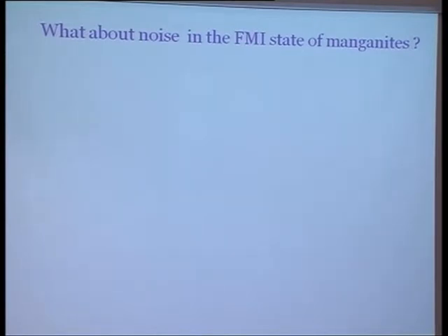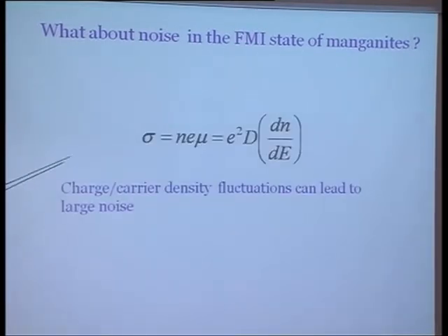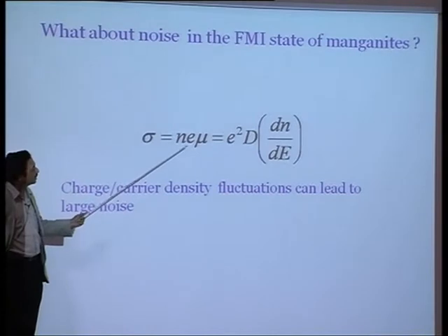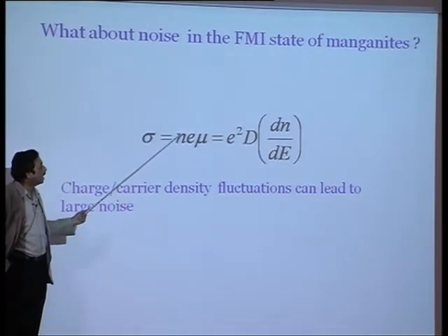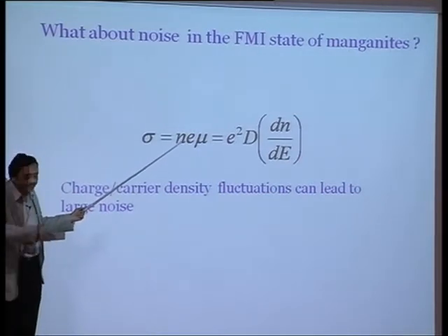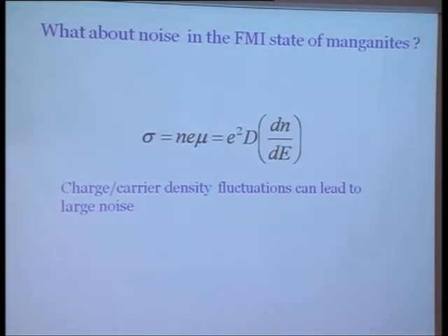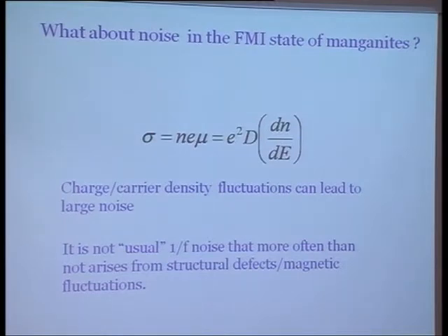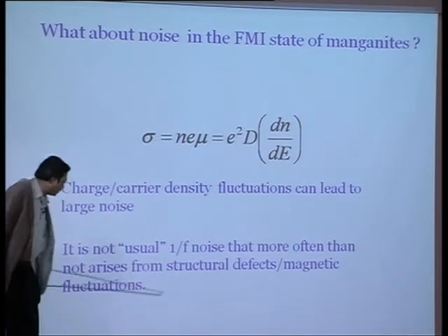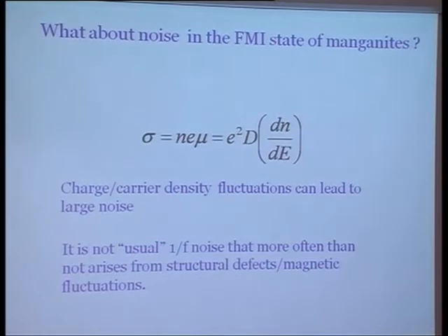So what about the noise in the ferromagnetic state of the manganite? Let me come back to this equation which Arindam has also shown, and which all of us born in the solid state physics community regard as our Bible. Here, just to tell you, you can get a conductance fluctuation either from this or from that. When you talk of universal conductance fluctuation, you are actually talking of fluctuation in the mobility, and the type of fluctuation that we'll be talking about, which is somewhat in the insulating state, is more in the fluctuation of the carrier density, n. So it is not the usual 1/f noise. The reason is that if you have a material which is not so good, if you made a film or something, you get an enormous amount of 1/f noise in it. And that 1/f noise most of the time comes from the mobility, as it happens in many magnetic fluctuations, for the charge carrier density is fixed over there.